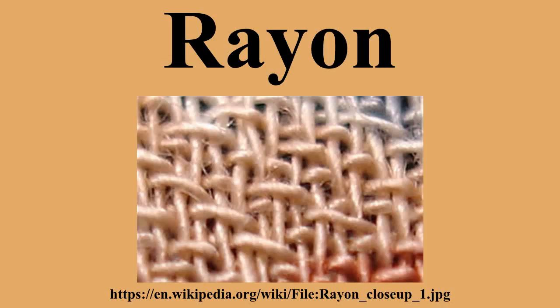Regular rayon is the most widely produced form of rayon. This method has been used since the early 1900s and has the ability to produce either filament or staple fibers. Production begins with processed cellulose. The cellulose is dissolved in caustic soda (NaOH + H₂O). The solution is then pressed between rollers to remove excess liquid. The pressed sheets are crumbled or shredded to produce what is known as white crumb. The white crumb is then aged through exposure to oxygen.